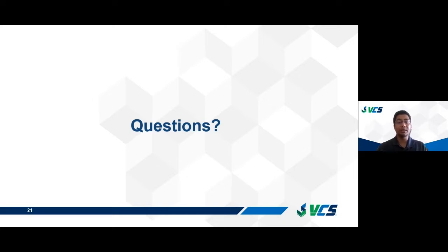That's an excellent question. There are several factors which contribute to the service life of any system, be it galvanized, metallizing, or fusion anodes. But typically, the factors can be like how much steel we are protecting, or what the exposure condition is. Does it have too much chloride exposure? Things like that. But typically speaking, metallizing can last anywhere from 10 to 15 years. But again, it is dependent on the conditions.